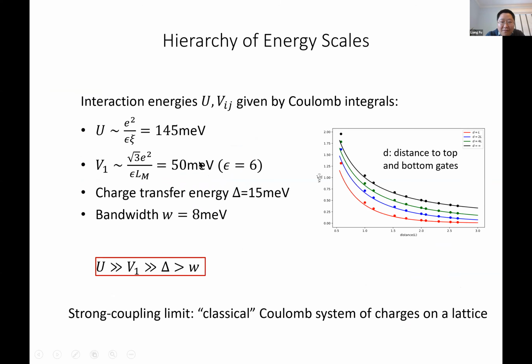So this is the energy scale associated with interactions, and this energy difference between the cation and anion, which we call the charge transfer energy, is about 15 millielectron volts. The bandwidth is the smallest energy scale, only about 8 millielectron volts. So interaction dominates, and also the on-site interaction is much larger than the first neighbor interaction. So what we end up with is a strong coupling limit.